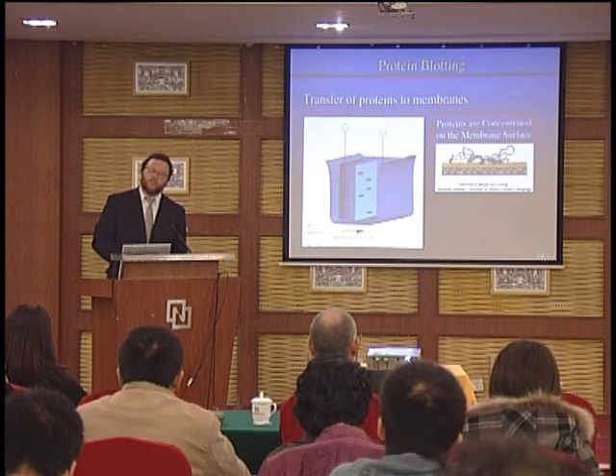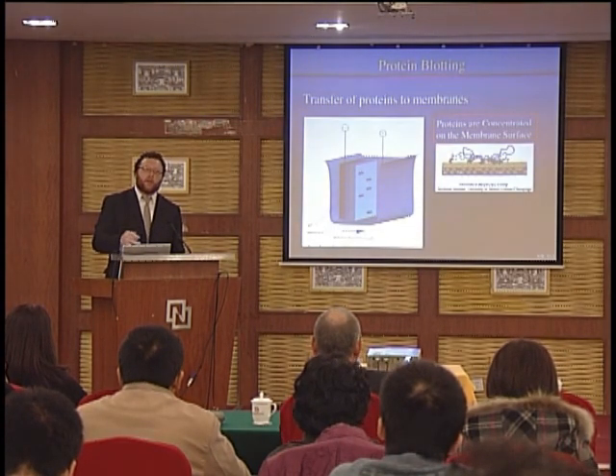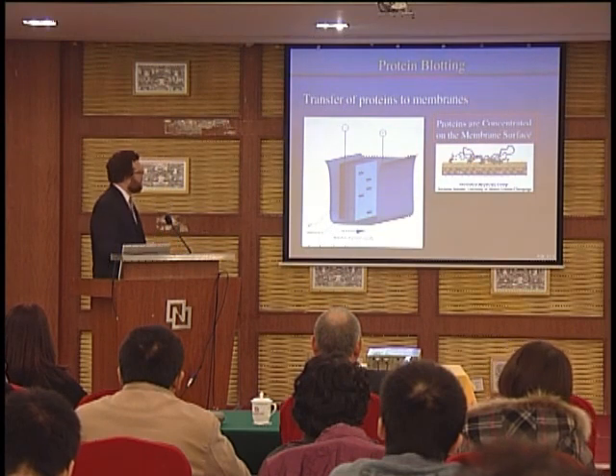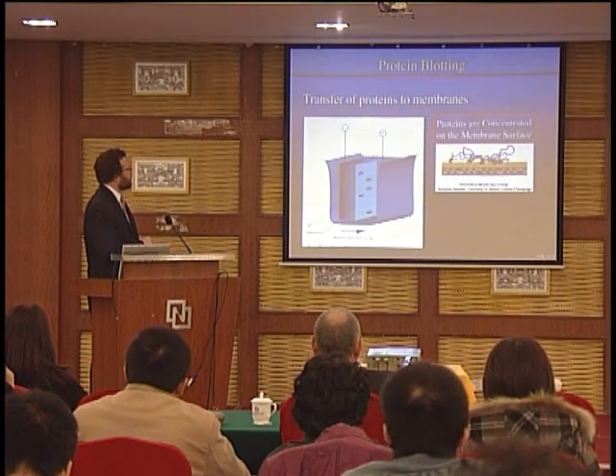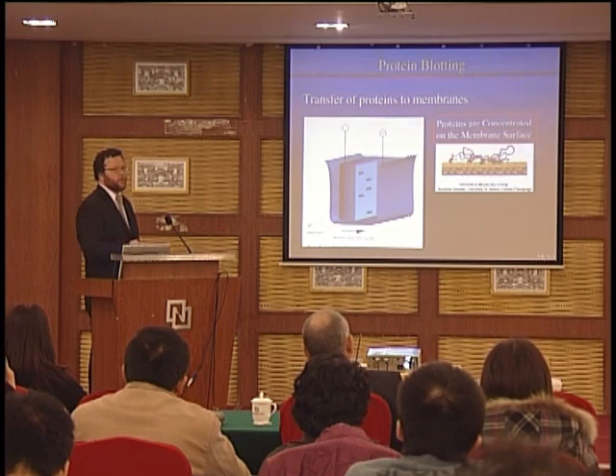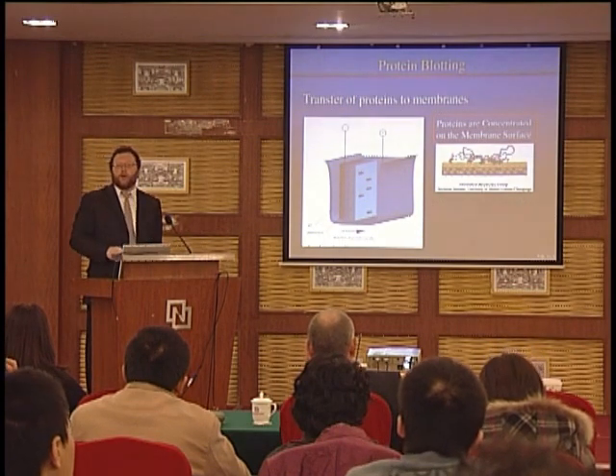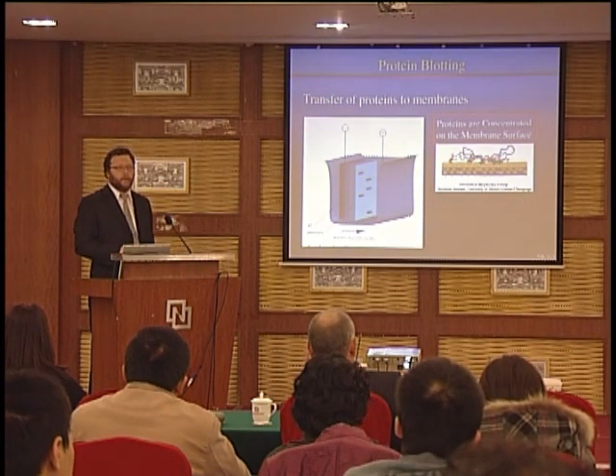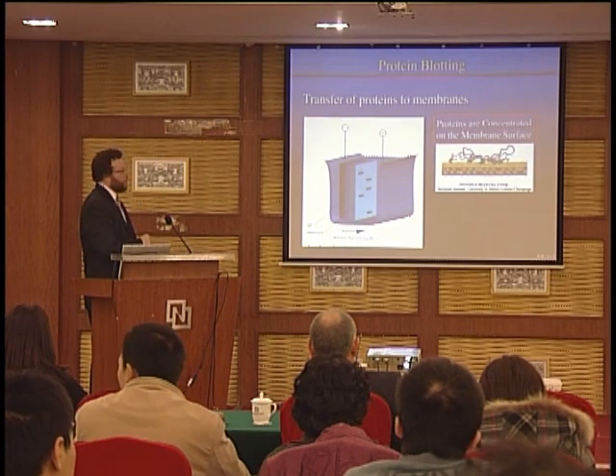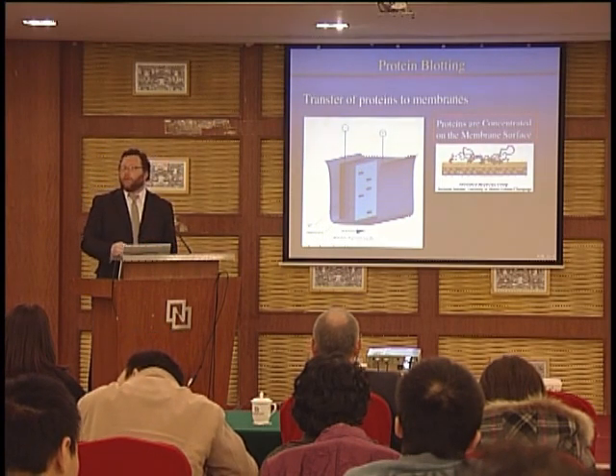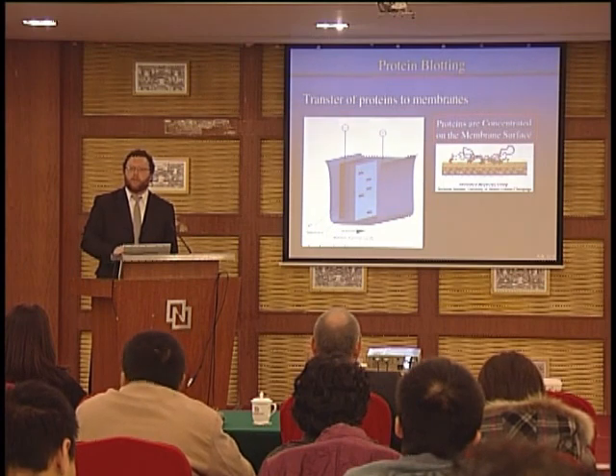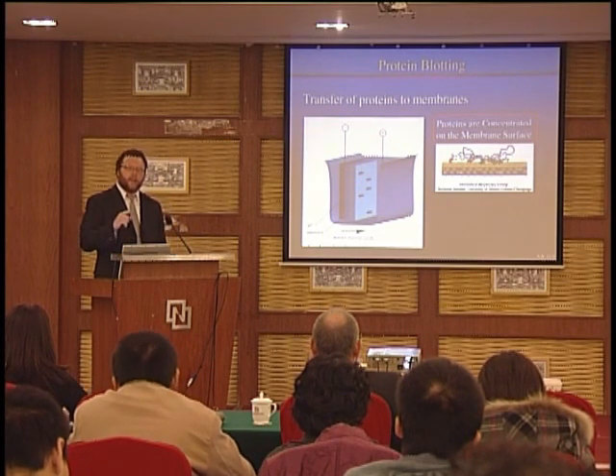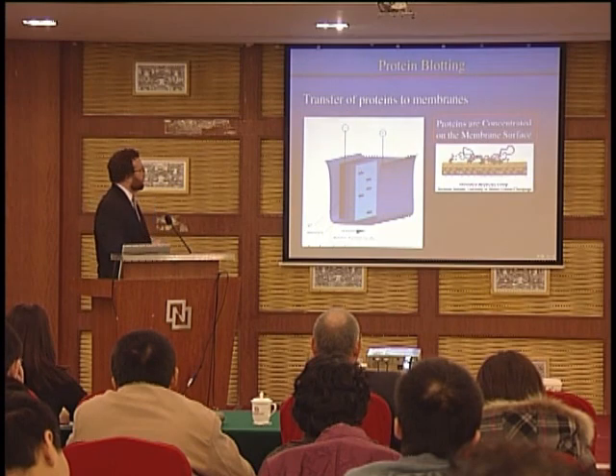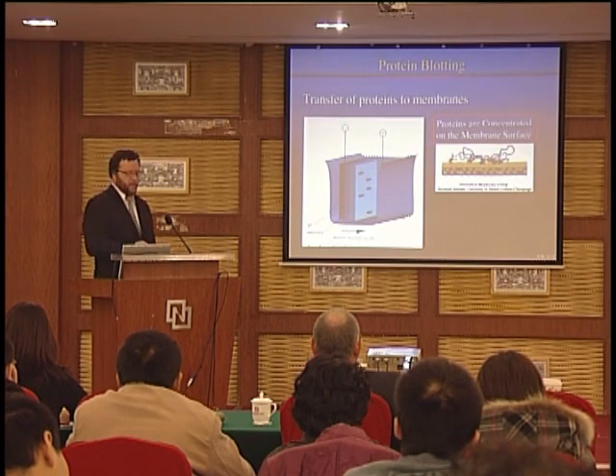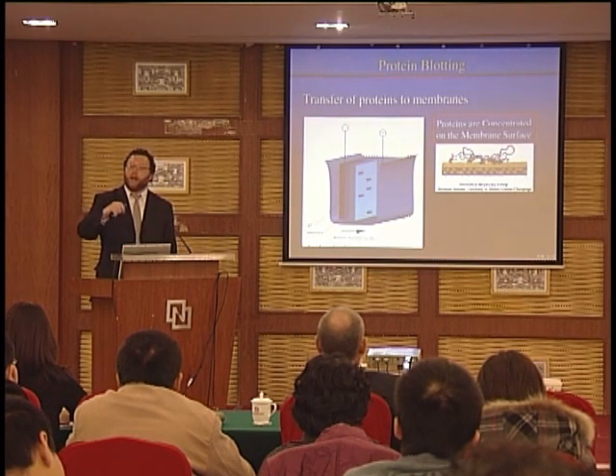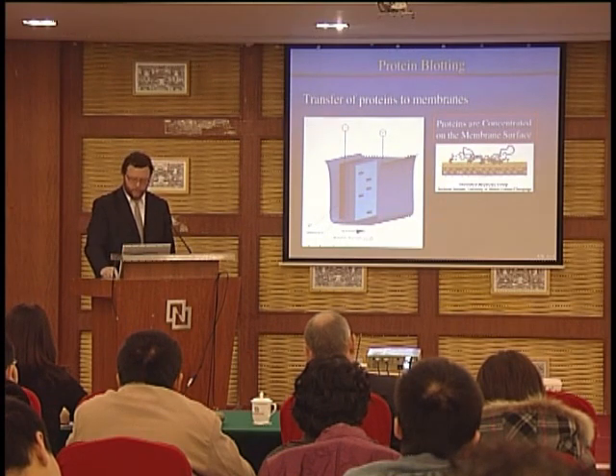The second step that's typically used is to blot that separation onto a secondary surface. In this particular example, I'm using electroblotting. So we just apply an electric field transverse across our gel electrophoresis membrane. And we take whatever was in the gel material and we put it right onto a secondary material. In this case, it's that PVDF membrane that we talked about before. And it has another advantage. The advantage here is that the proteins are now concentrated on the membrane surface, which means we have a high surface concentration that we can work with.